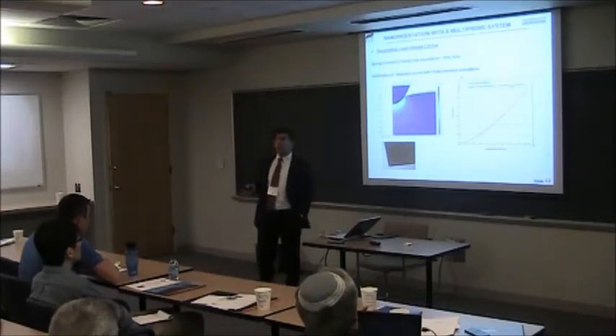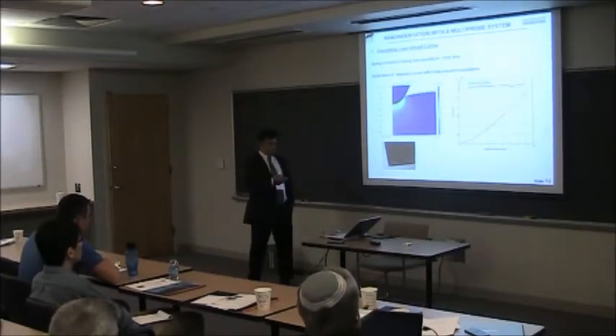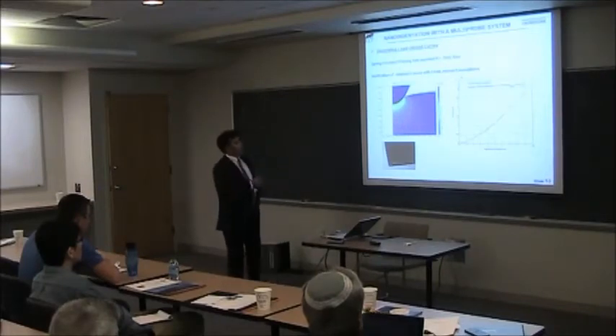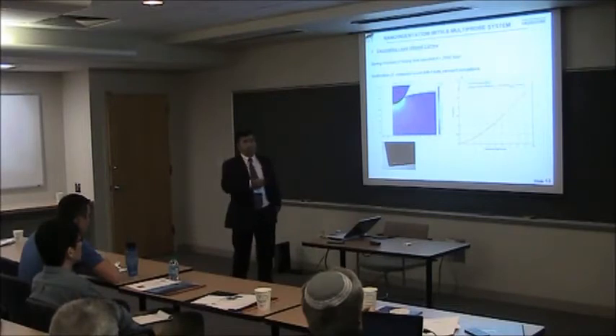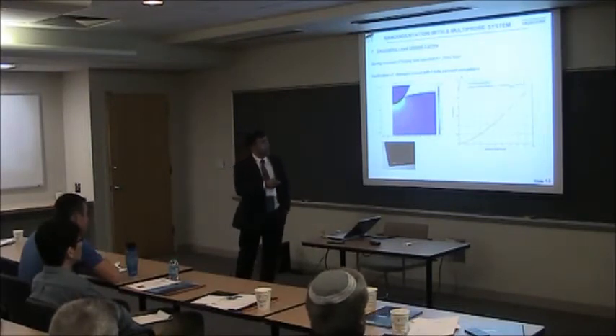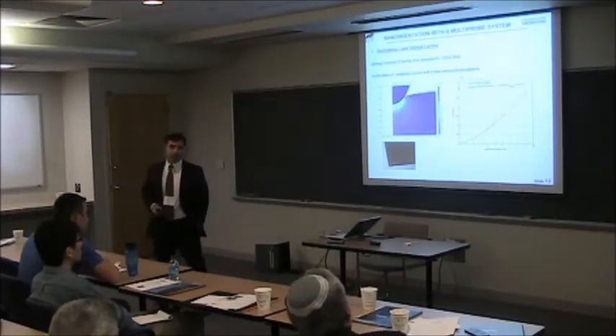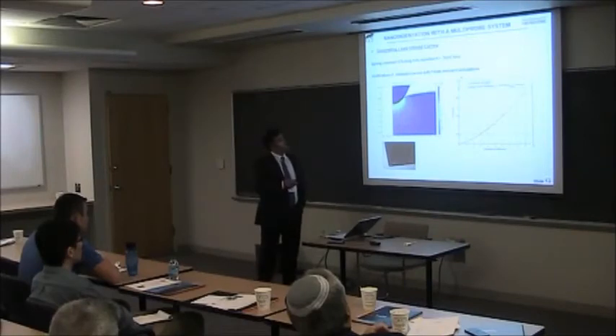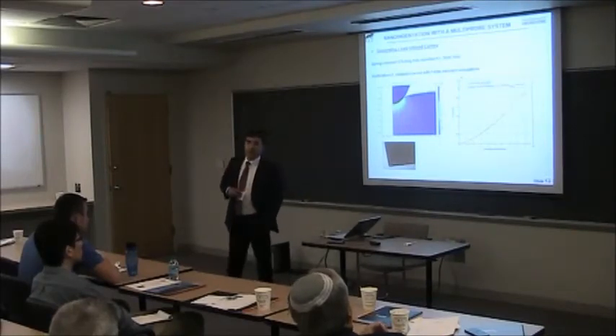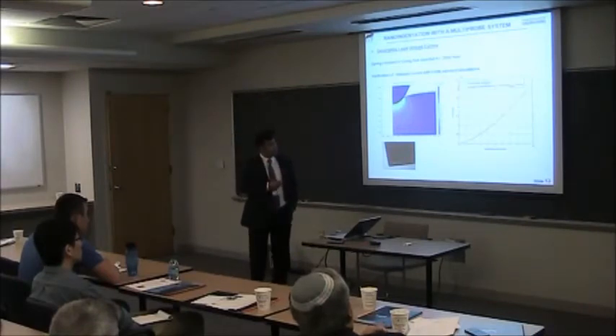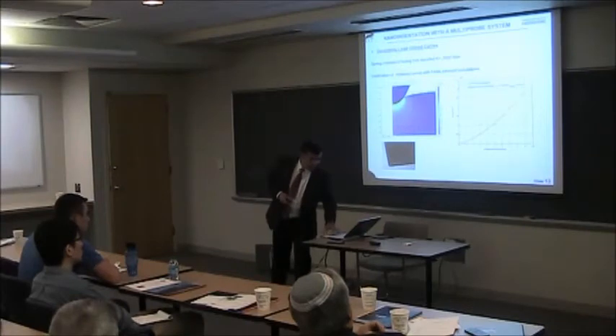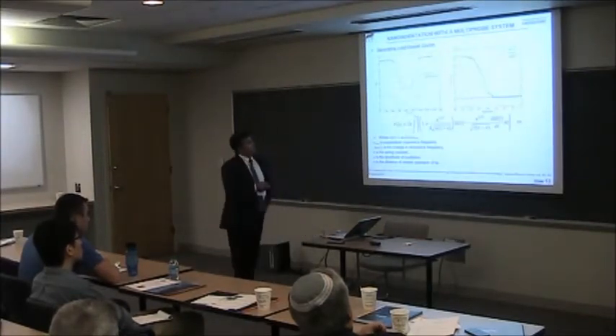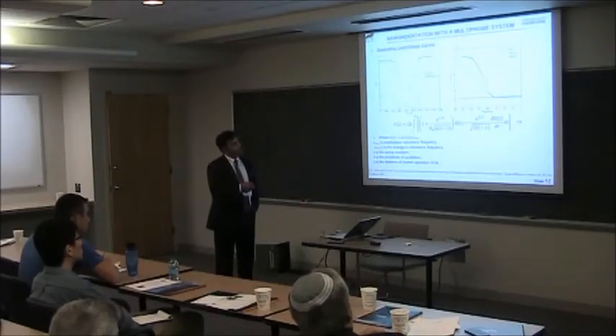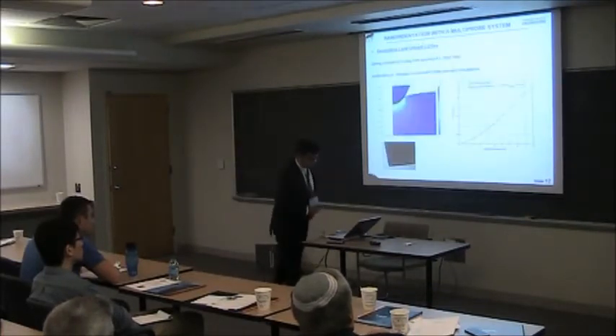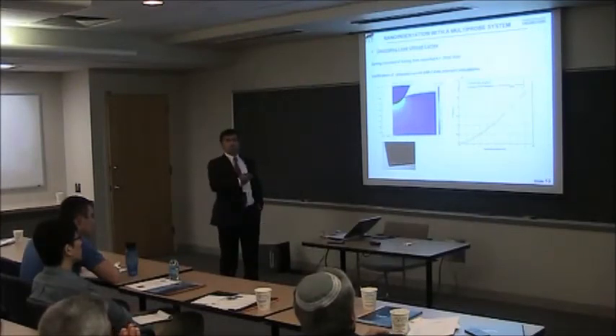Well, maybe we can simulate it in COMSOL realistically and see how it is. So what we did is we simulated the whole nanoindentation in COMSOL by using the material, using the radius of curvature, and obviously we couldn't indent all the way to 200 nanometer because it's huge. The meshing was a huge issue in COMSOL. Well, we were able to indent up to 10 nanometer, and the value that we got is about 30 micronewton level, and in the previous one, 30 micronewton around here, which is about 10 nanometer too. So we could simulate only this part, really, because of the computational limitations. So everything is so far so good.